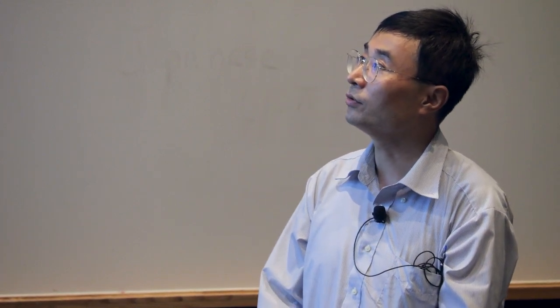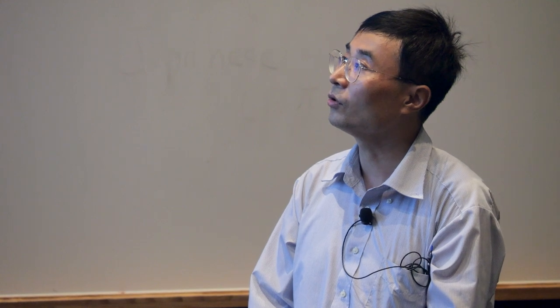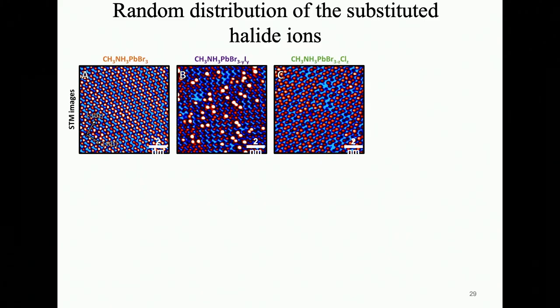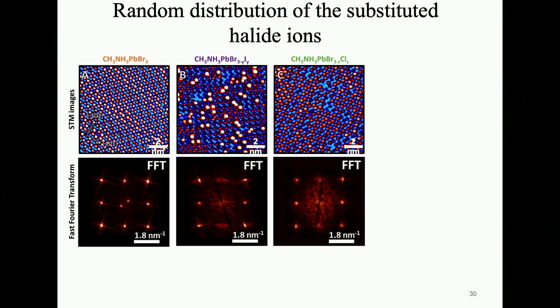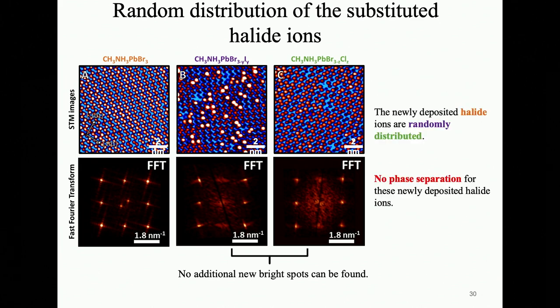Then we scanned larger regions of all these three samples, to try to determine whether these additionally deposited halide ions form any specific ordered structure. The top row shows the large area scan STM experimental images for all these three samples. The bottom row shows the corresponding fast Fourier transform images. As you can see, for both types of the mixed halide perovskite samples, there are no additional new spots. This suggests that the newly deposited halide ions are randomly distributed. There is no phase segregation for these additional ions.